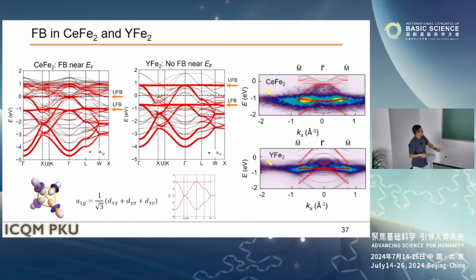Our collaborator did some calculations on those compounds. You remember for a pyrochlore lattice, you should see this flat band with a band touching point around the gamma point. However, these two compounds have time-reversal symmetry breaking because they are ferromagnetic. So this doubly degenerate flat band will split into an upper flat band and a lower flat band. Right? Unfortunately for yttrium, the Fermi level is located between them, so you cannot see too much signature of a flat band. However, for cerium iron 2, because this one has one more electron than yttrium, cerium 4+, yttrium 3+.